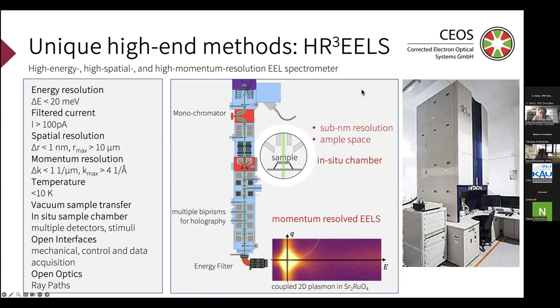Also, we developed these methods, the so-called high-resolution EELS machinery. So it's TEM-based, so it's connected to Axel Lubk. Axel's professorship is paid by a company, which is really dealing with optimizing such objects like the monochromators or filters here, and together with the company we are developing this spectrometer. At the end of the day it looks like a usual electron microscope, but in situ there are monochromators. There's a special sample space which allows cooling down to helium temperature. And there's an energy filter which allows us to measure the energy of the electrons with extremely high resolution.